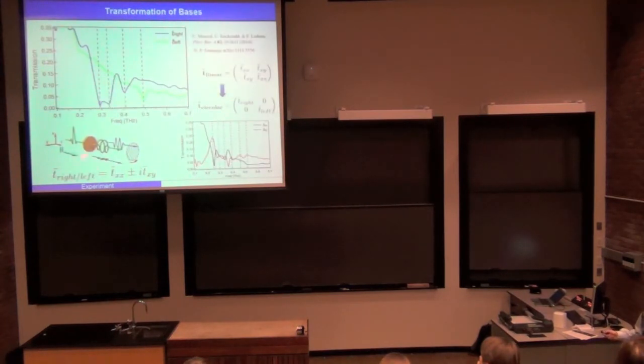And as I was saying earlier, if we apply a magnetic field along this direction, then the spins would be precessing around the magnetic field, more or less. As a result, you would expect absorption in one of the circular channels. So this tells us it's really not right to look at this absorption in linear frames. For example, we shouldn't look at it in Cartesian laboratory frame, but it would be much better to look at the spectrum in circular frame. And because we do time domain measurement, the data we obtain are all phase sensitive. As a result, we are able to perform this transformation of basis.